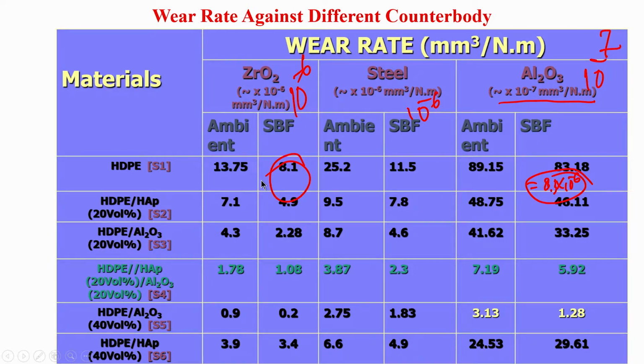Now let us look at this table a little closely. If you compare between ambient and SBF, there is a reduction in the wear volume: 7.1 goes to 4.9, 4.3 goes to 2.28, and so on. Similar observations can be made in case of the steel counterbody also: 25.2 goes to 11.5, 3.9 goes to 2.3. In case of alumina, 89 goes to 83, 41 goes to 33.